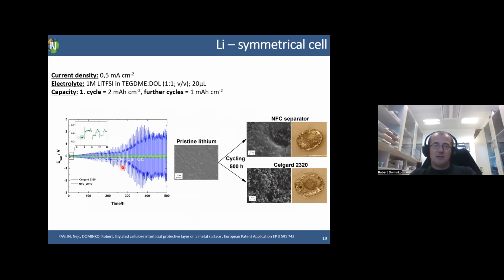And working on that, we can see some improvements. Still, actually opening the cell, we see that after 500 hours of working, lithium metal is not degraded so much if it is in contact with the cellulose as compared to only with the Celgard separator. But that's not actually what we were looking for.